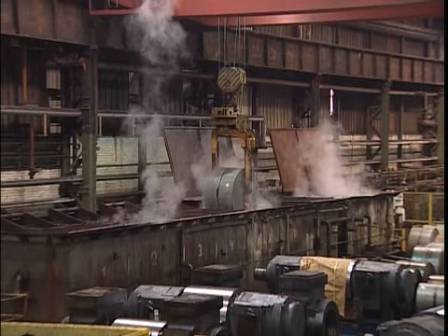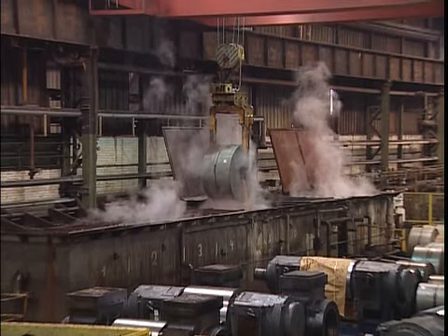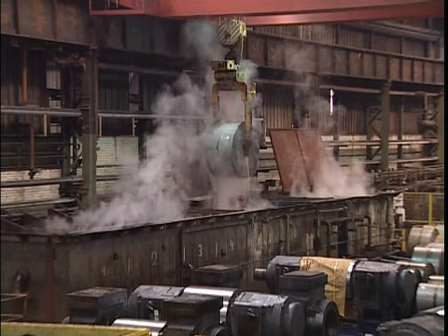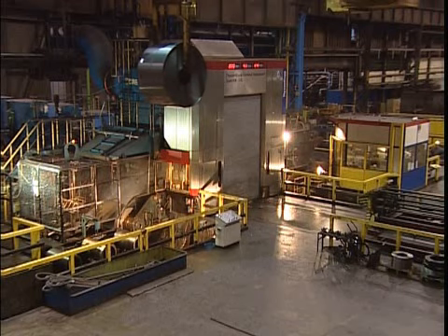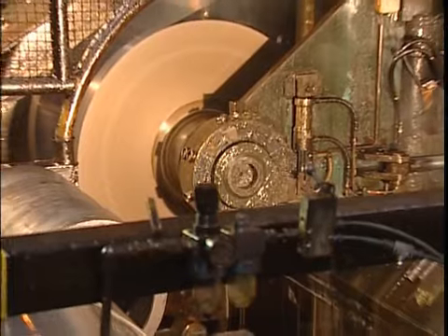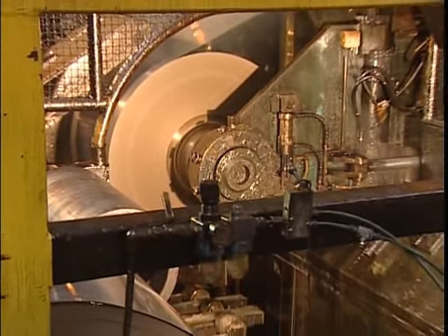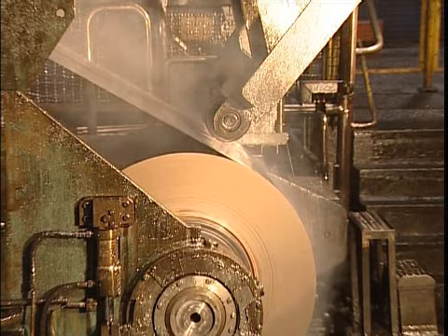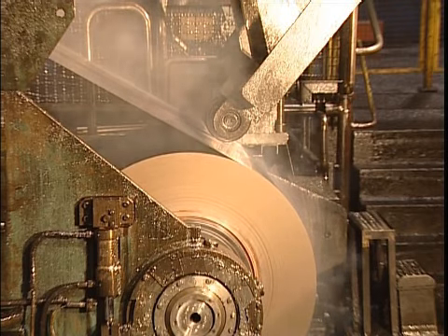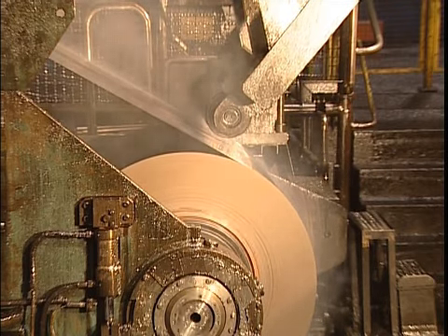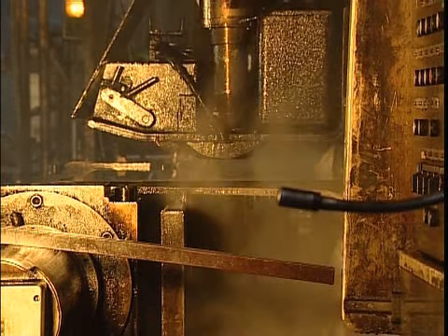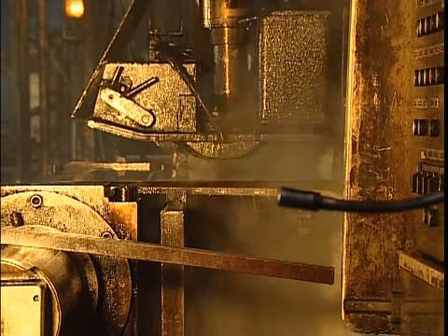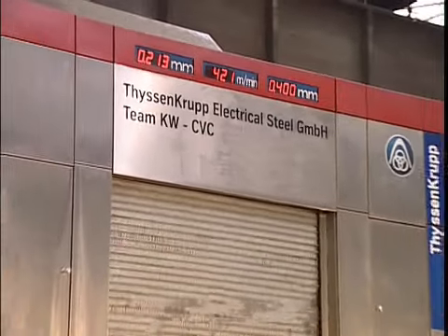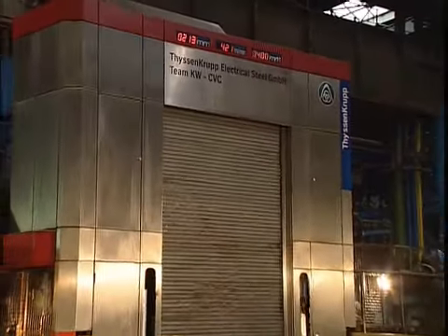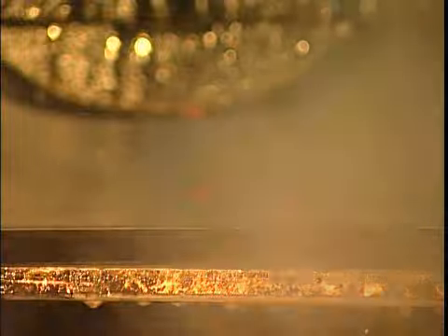After pickling to remove the hot band scale, and before cold rolling, we need to warm up the band again in a bath of hot water. The special cold rolling mill rolls the strip according to a predetermined reduction schedule. In the first instance, we roll Power Core C to an intermediate thickness, while Power Core H is reduced directly to the final thickness as requested by our customers. The tolerance on thickness is in the range of only a few micrometers.